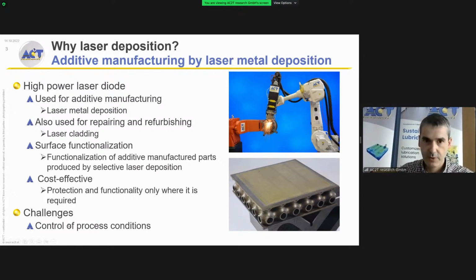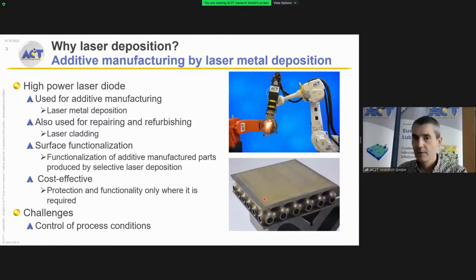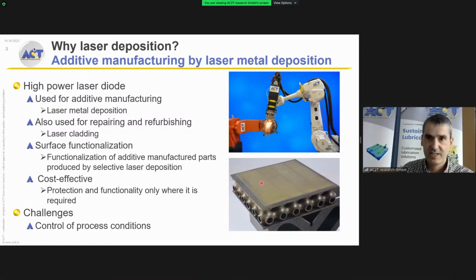So like, for example, in this example here in the bottom, so let me put the pointer. In this sample here, you can have a sample manufactured using, for example, selective laser melting, and on top of it, you can have a laser metal deposition for surface functionalization. So this is a very convenient method, very modern approach. It's a novel manufacturing approach, but it also has some challenges in the material deposition.